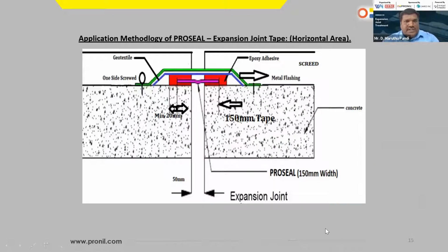Application methodology of the ProSeal expansion joint tape on a horizontal area. Just imagine that we will be working on a podium slab or a walkway or a pathway in a construction system. So I'm just mentioning a small drawing. Consider a 50 mm expansion joint in a podium slab where traffic or car parking will be there. For this 50 mm, I'm selecting a tape of 150 mm. This pink one is going to be the 150 mm tape, which is fixed with the epoxy adhesive. This epoxy adhesive has to be maintained at a thickness of 4 mm on the substrate.